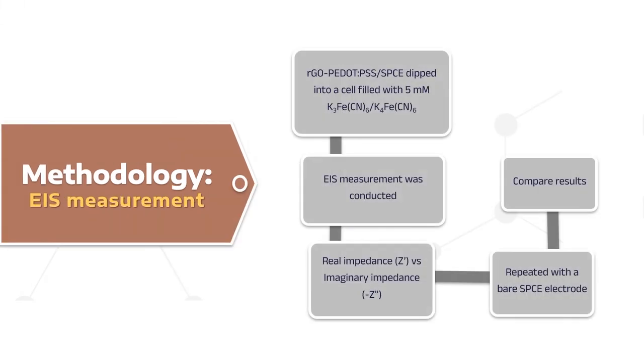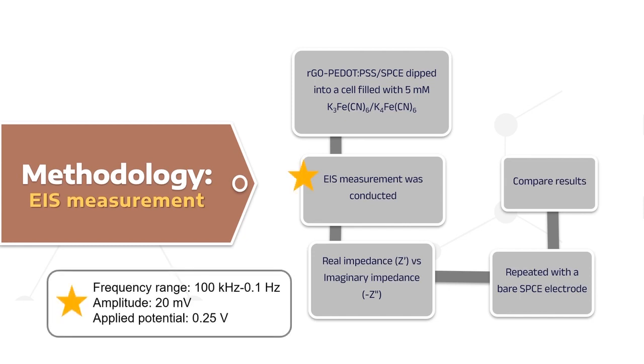The reduced electrode was dipped into a cell that was filled with 5 mM K3Fe(CN)6/K4Fe(CN)6, 1:1, in 0.01 M PBS. It was ensured that all electrodes were immersed in the solution. This measurement was conducted following the conditions. The obtained data of real impedance versus imaginary impedance from the EIS measurement were observed and recorded. To compare the results, the above steps were repeated with a bare SPCE electrode.